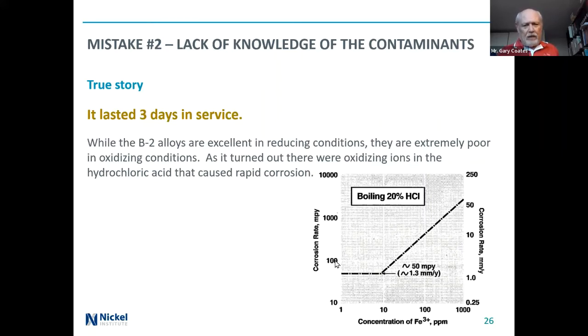The picture on the right shows that at even up to 10 parts per million ferric ion, it really didn't have a lot of effect, but above 10 parts per million, the corrosion rate starts to skyrocket. So you have to be very, very careful with these kinds of alloys. They're excellent in strongly reducing conditions. They're not so good in oxidizing conditions.